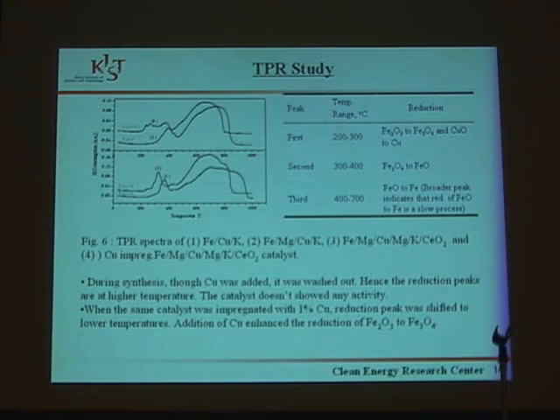The TPR study shows that curve number 1 is the precipitated iron catalyst, then curve number 2 is the magnesium promoted precipitated iron catalyst. Due to magnesium, the reduction temperature of the catalyst is decreased. Then here this is the catalyst which is iron magnesium supported on ceria, but it has no copper in it. Even if it is taken during synthesis, the copper has leached out during the synthesis, and therefore the reduction temperature was high. When this catalyst was again impregnated with copper, it has shown reduction at low temperature.